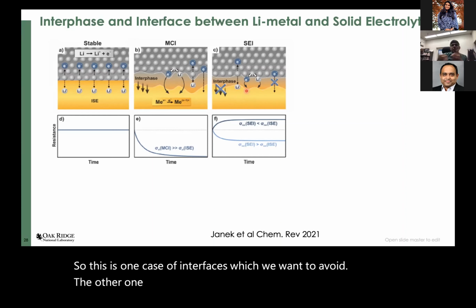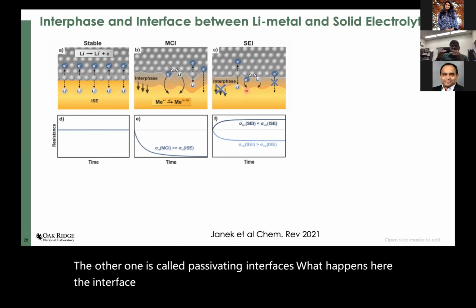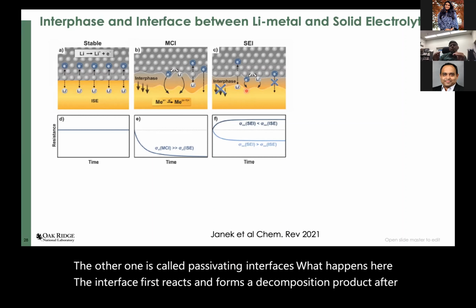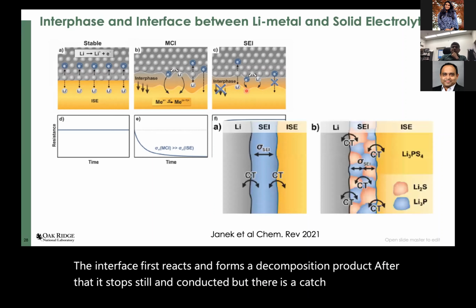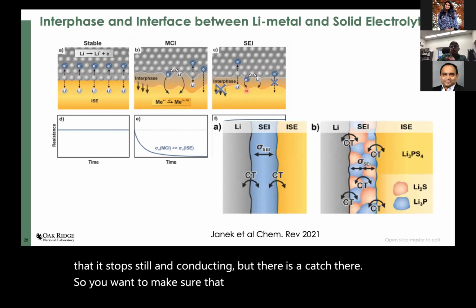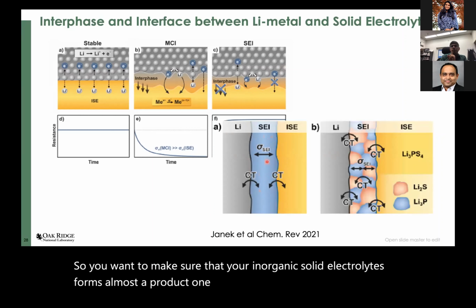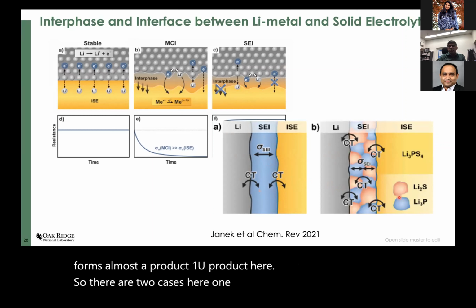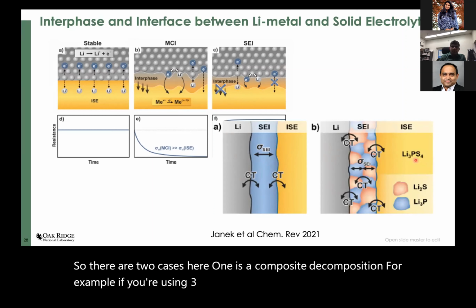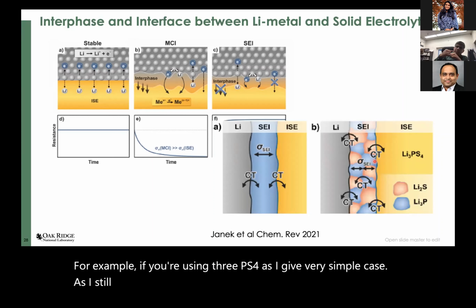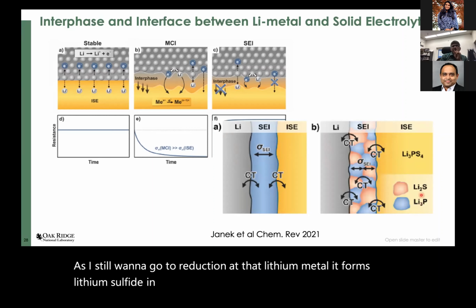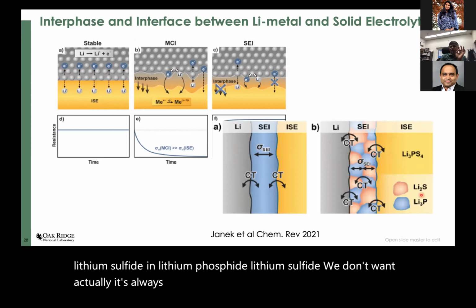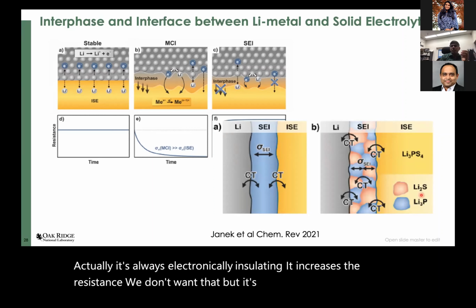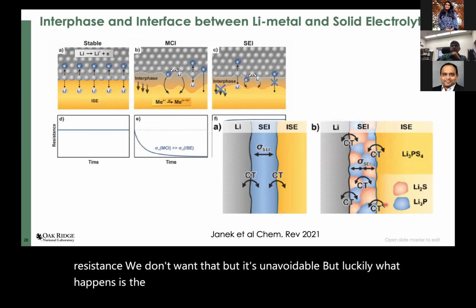The other one is called passivating interfaces. What happens here, the interface first reacts and forms a decomposition product. After that, it stops, still ion conducting, but there's a catch there. So you need to make sure that your inorganic solid electrolyte forms almost one uniform product here. So there are two cases here. One is a composite decomposition. For example, if you are using Li3PS4, as I give a very simple case, when you go to reduction at lithium metal, it forms lithium sulfide and lithium phosphide. Lithium sulfide, we don't want actually. It's always electronically insulating. It increases the resistance. We don't want that, but it's unavoidable. But luckily, what happens is the lithium phosphide phase can form this kind of domain so that it's very highly lithium ion conducting.